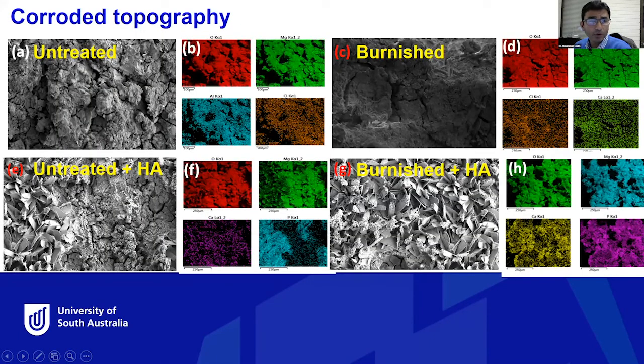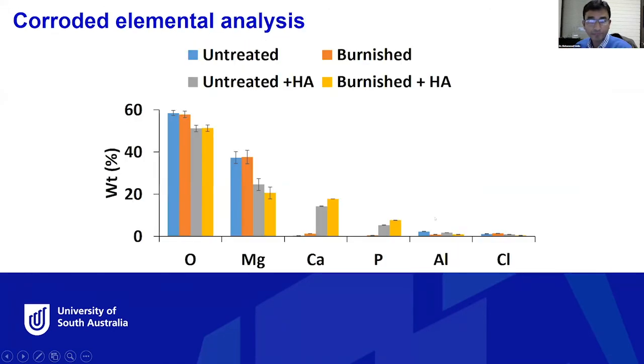And we have got some corroded topography, just to show you that the burnish plus HA coating actually preserves the surface pretty well. Compared to that, the burnished surface has significant corroded products, and in the case of the untreated surface, it is quite high. So that means the burnish plus HA coating gives an additional corrosion barrier and protects the surface here.